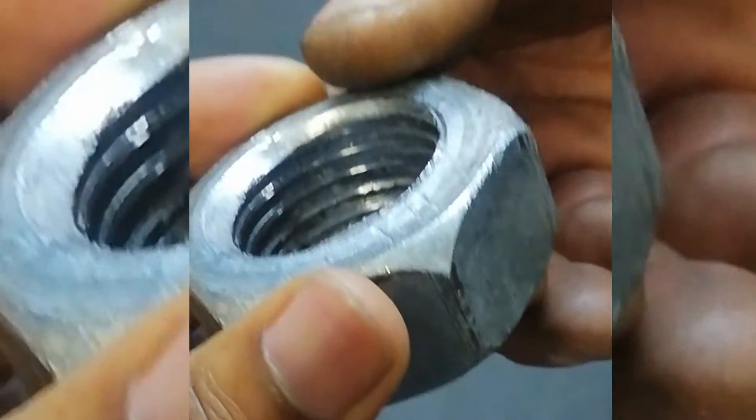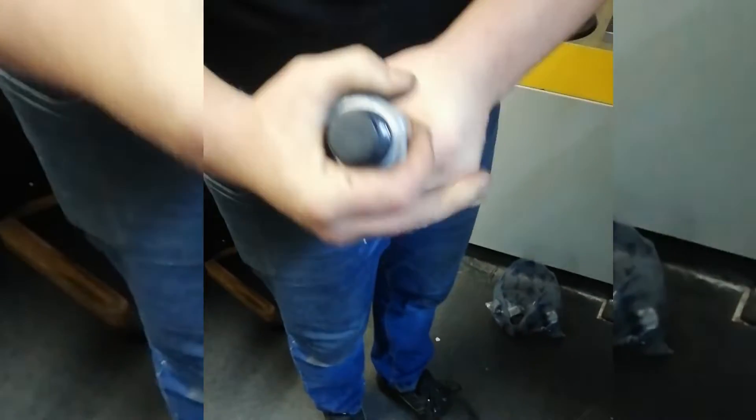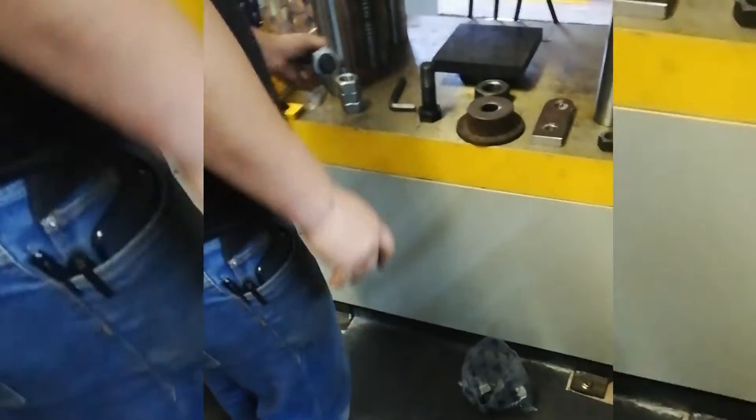The whole thread came out — that's something to watch for. Usually doing it with hardened bolts because we can use the hardened bolts or the mandrel, which is also hardened. So this one passed the test. Now do it — with the fingers, if it doesn't turn freely, then this is a failure, even though it has not broken or stripped. If it won't turn, it has failed.